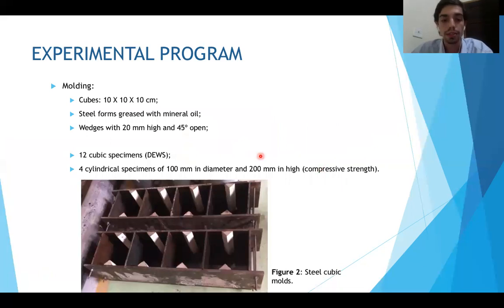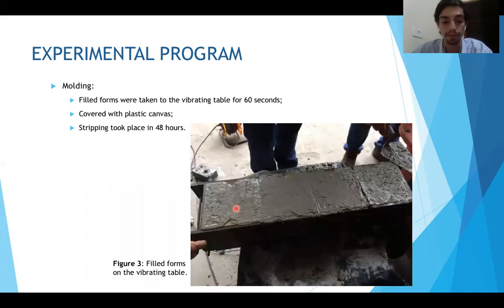The specimens were molded in steel shapes with wooden wedges fixed on the sides. These wedges are 2 centimeters wide and 45 degrees open. 12 cubic specimens with a 10 centimeters edge were molded for the DEWS test, and 4 cylindrical specimens with a diameter of 10 centimeters and a height of 20 centimeters for the compressive strength test. All forms were greased with oil to facilitate stripping.